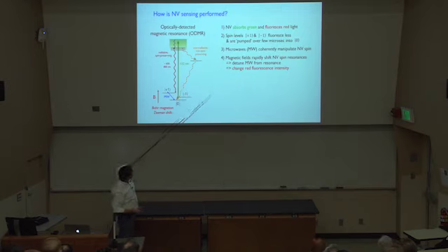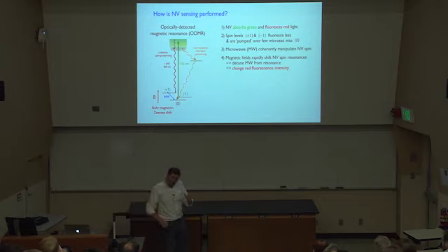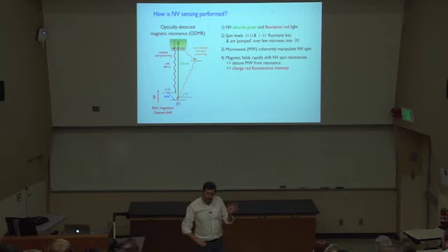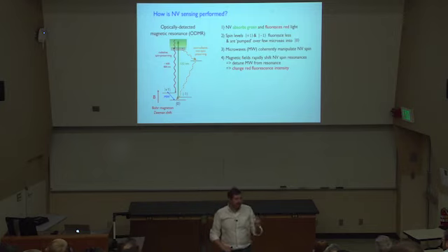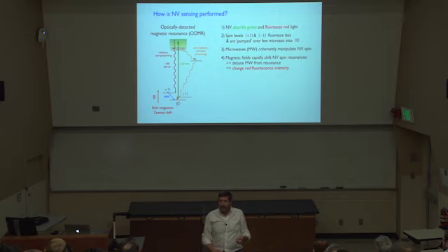It turns out, however, that the plus and minus 1 levels fluoresce less, at a lower rate than the ms equals 0 level does, because they can decay through the small spin-orbit coupling via this metastable state and preferentially back down to ms equals 0. So let's think about that for a second. If the NV happens to be, or part of its wave function is, in ms equals 0, and you illuminate with green light, it's going to absorb the green photon and emit a red photon, and then repeat that over and over again. It's just a cycling transition.